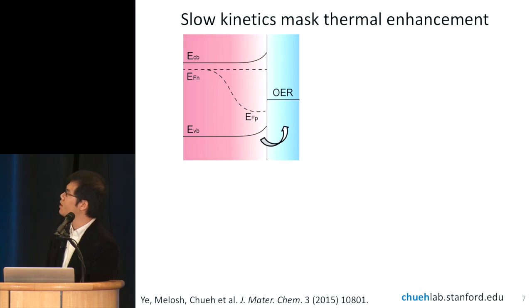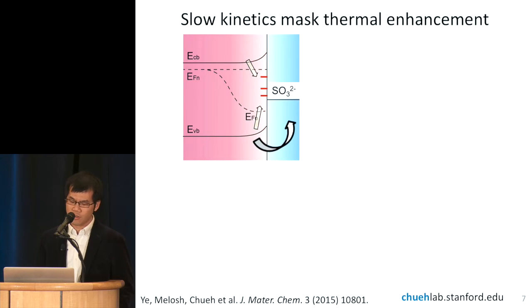So we went back to simple electrochemistry and looked at how the carriers are being generated in the material. It turns out that in the material we're looking at, the activity at the surface, the efficiency for the material to extract the carriers into the solution, is actually quite slow. So all the benefit you get from enhancing with temperature may just get eaten up by the recombination process at the interface.